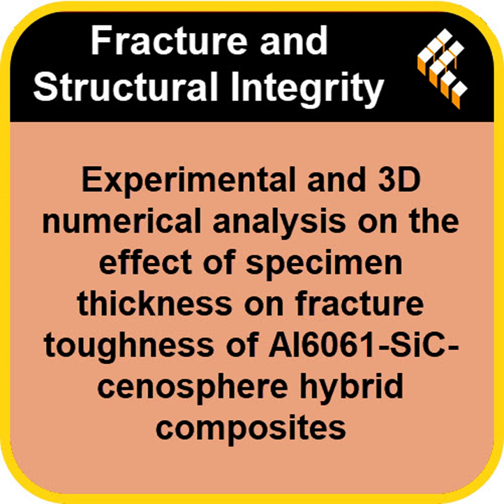The scanning electron microscope, the SEM images told the real story, the microstructure. And what did the SEM show? What was the difference? Well, the 3 wt% and 6 wt% cenosphere samples look great. Fantastic particle dispersion, really strong bonds it looks like between the aluminum matrix and the reinforcements. Yeah. But the 9 wt% loading showed significant agglomeration. Agglomeration, so clumping. Exactly. The particles just clump together into these big, useless masses within the aluminum. And these clumps instantly create huge stress concentration points. They introduce porosity. It just destroys the mechanical properties you were hoping for.